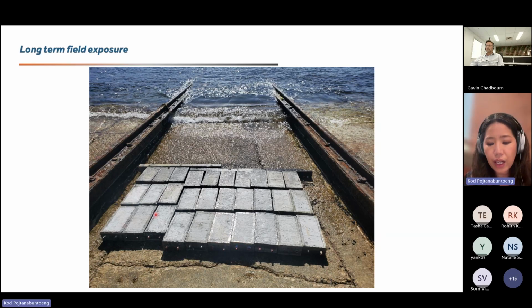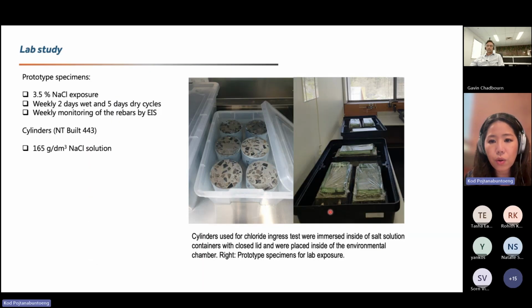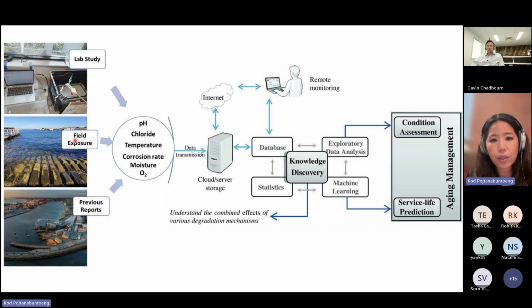A representative of each of the mix designs is also within the lab. In this case, we do the accelerated test, so we do cycling of the exposure to seawater. The cylindrical samples are also exposed to seawater, for the future chloride testing.